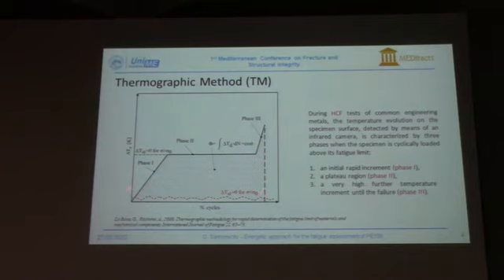A first phase where we have an initial rapid increment, then in the second phase the temperature reaches stabilization, until in the third phase we have a very high temperature increment until the failure. If we stress the material below the fatigue limit, we usually don't see anything in a thermal way. The area subtended by the temperature versus number of cycles curve could be related to an energetic parameter phi that we can assume constant given the test frequency and the stress ratio.